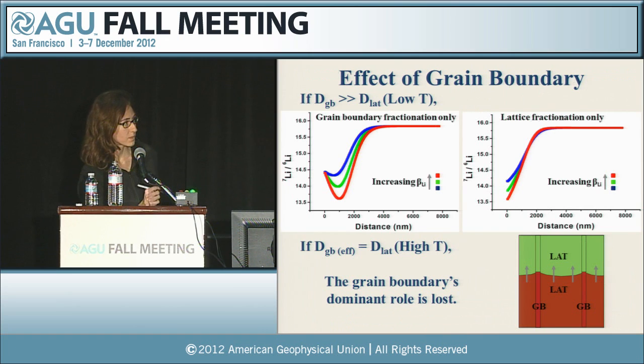So these are just some of the results for when the diffusivity in the grain boundary is many orders of magnitude greater than the diffusivity in the lattice. So this would be sort of equivalent to a low temperature type of experiment. So in both of these graphs, we have lithium-7 over lithium-6 plotted as a function of distance away from the source.